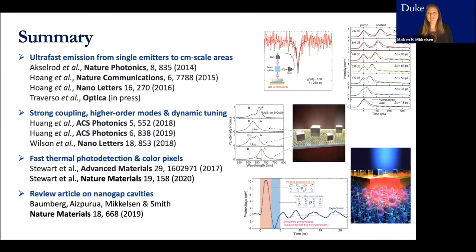Yes, that's a good question, and something that we have certainly studied in great detail. Typically we see if the film is too rough, it's not ideal at all. If this film gets too rough, we end up not being able to see a large area plasmon resonance because the variation from cube to cube is just too great. So typically we have a roughness less than a nanometer, RMS roughness.